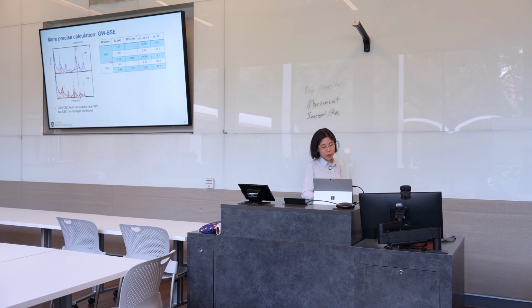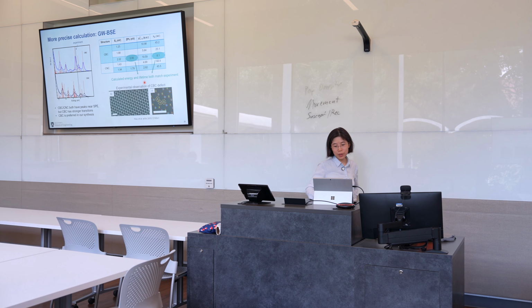We can further look at some metrics. Here we can see these values for CBC match very well with our experiment. So this further confirms our sample is CBC dominant. Basically, CBC is a better emitter than CNC, and it's dominant in our sample, making our sample a better single photon emitter. Actually, after we submitted our work, we found another work posted on arXiv, and they confirmed the experimental observation of the CBC defect. This gives us more confidence that we actually have CBC in our sample.